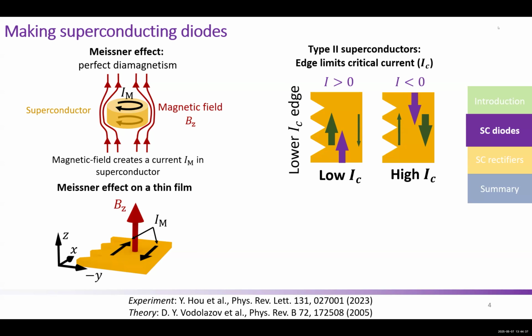Now, we are using a type of superconductors which are called type 2, where the edges are actually the ones which limit the critical current. And that actually means that because we have made these notches here, we have reduced the critical current of this edge, and now by controlling the direction of the current, we can have a low critical current in this direction and a high critical current in this other direction. However, this technique requires a magnetic field to be applied on the sample, and we want to get rid of that. So what we do is the following.